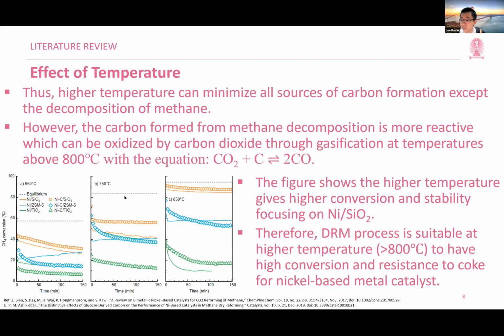And as you can see in this figure below, if we increase the temperature from 650 to 750 and 850, the initial and final conversion of methane actually increases significantly. This draws a conclusion that the DRM process at higher temperature has a high conversion and resistivity to coke for the nickel-based metal catalyst.